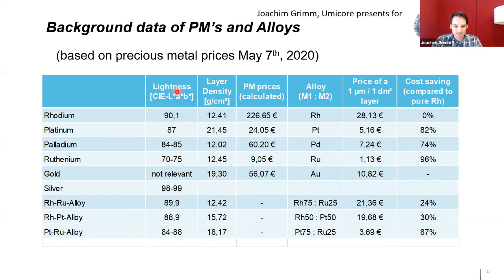The whiteness, described in this line, is the most white and light one compared to the other white platinum precious metals like platinum, palladium or ruthenium. The lightness, the L value, is 90 at rhodium, which is the whitest of the platinum metals. Next would be 87 at platinum, palladium around 84 to 85, and ruthenium just 70 to 75. I have gold here as a comparison, we need that later on, and I put silver as a comparison. Everybody knows how white silver looks, and pure silver has a whiteness of 98, 99 in this calculation.